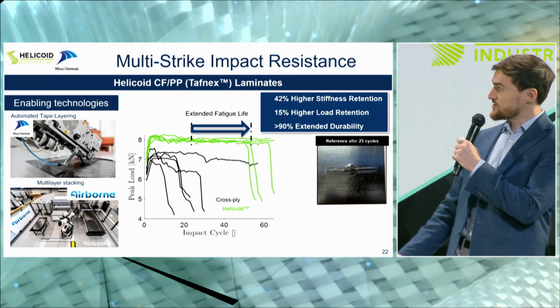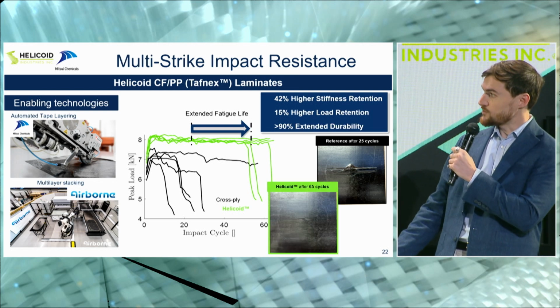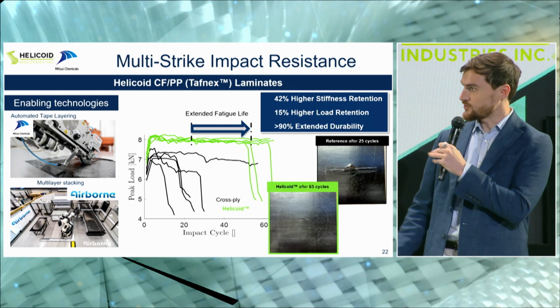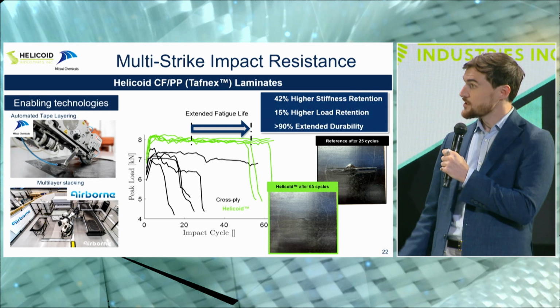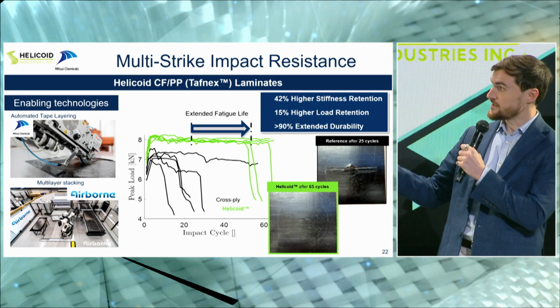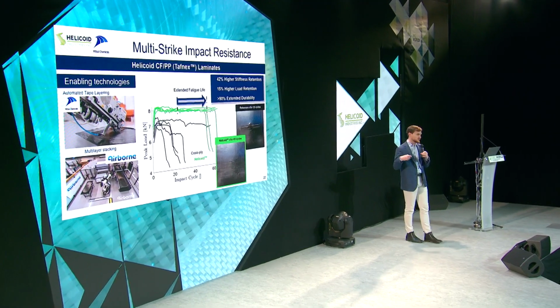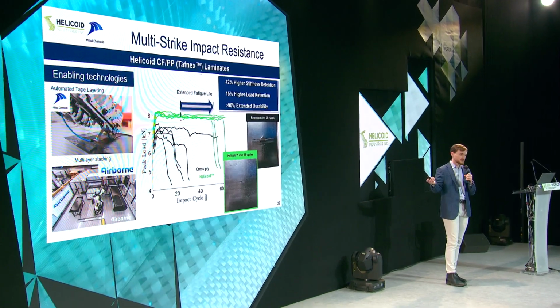These are two images that I hope you can see quite clearly. Otherwise, feel free to come to our booth to have a look at the proper sample, where you can see the damage accumulated in the reference cross-ply after 25 impacts, full perforation, lot of fiber failure, while in our case, after 65 impact cycles, you see very little damage still in the structure.